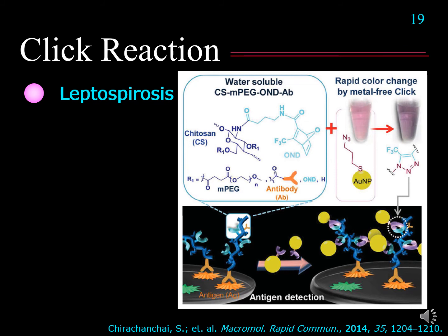So if we have gold nanoparticles modified with N3 mixed with it, starting from the antigen on our sample holder, the antibody attaches on top of the antigen, and then we mix the gold nanoparticles with azide on top. The azide can then react with the alkyne, and at the end, the gold nanoparticle is now caught or stuck onto our sample holder.